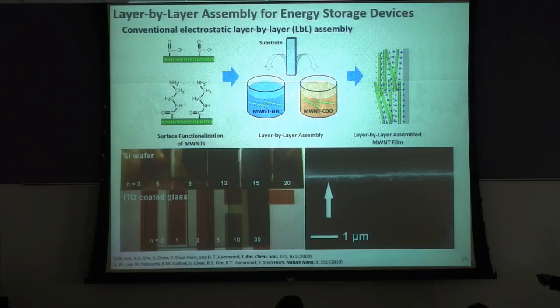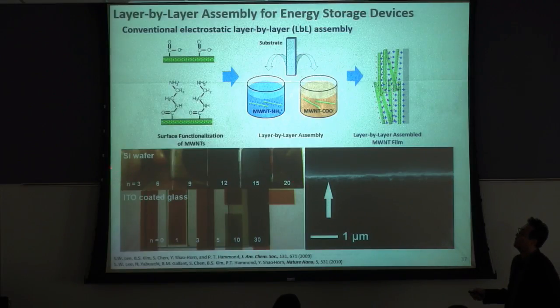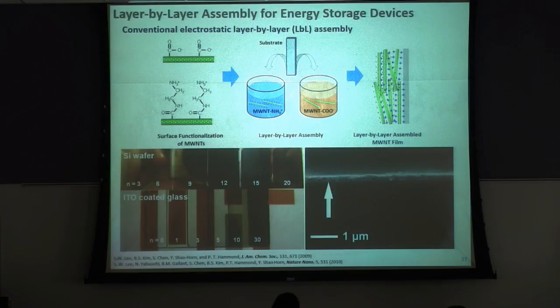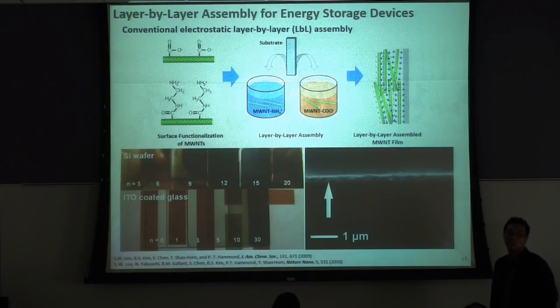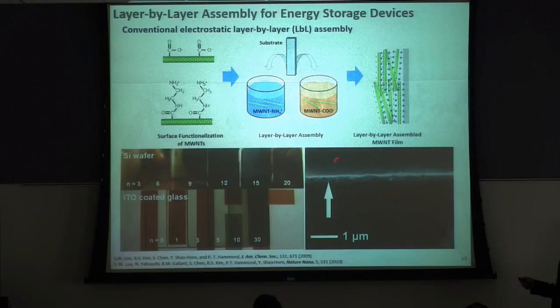Let me call this kind of dipping one bilayer cycle. Then if we increase the bilayer cycles, we can increase the thickness of the carbon nanotubes on the surface of any kind of substrate, such as silicon wafer and also ITO-coated glass. So we can linearly increase the thickness of this carbon nanotube film by controlling the bilayer number. Then this is a cross-sectional SEM image of the carbon nanotube film on the silicon wafer. You can see conformal, uniform thickness of carbon nanotubes, and this white arrow indicates the interface between the carbon nanotubes and the silicon wafer.